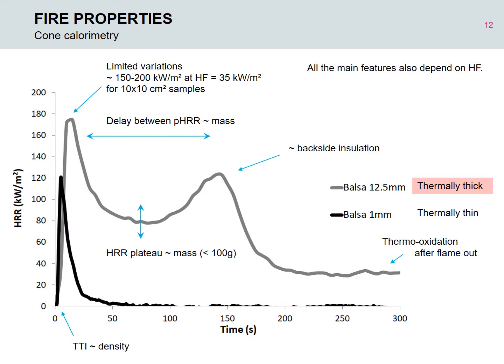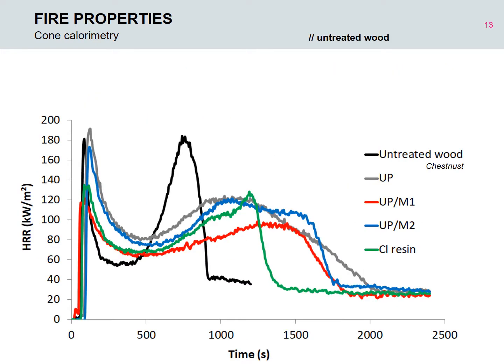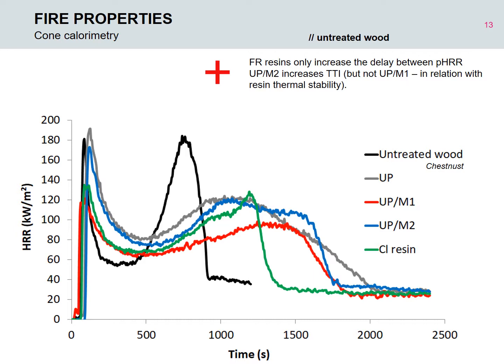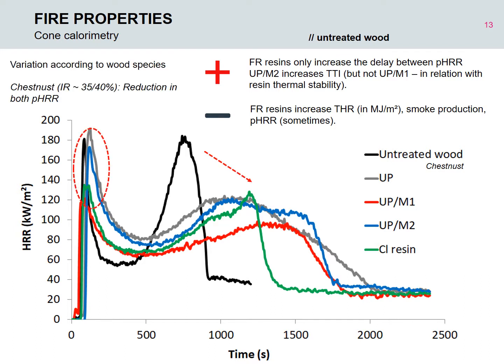The delay between the peaks of heat release rate depends mainly on the sample mass. In comparison to untreated wood, the resins increase the delay between peaks of heat release rate because the density, and so the sample mass, increases. The resin containing the monomer M2 also increases the time to ignition because this resin is thermally stable. But in many cases, unfortunately, the resins increase the total heat release in megajoule per square meter, the smoke production, and quite often the peak of heat release rate. Here I present the best results obtained with chestnut, with the impregnation ratio between 35 to 40%. And in this case, we observe a reduction of both peaks of heat release rate. But it's not a general observation.